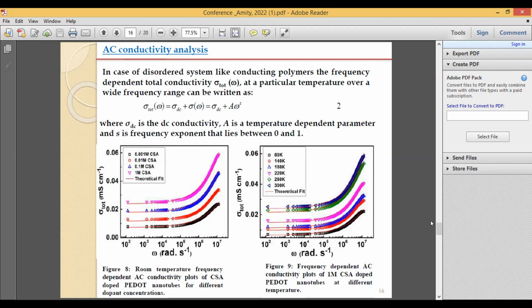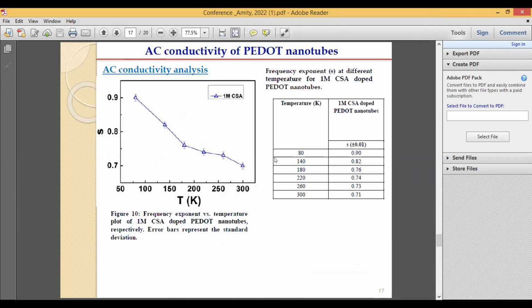doped sample at different temperatures with this equation number 2. From there we have found the value of S, and it is seen that the value of S is found to decrease with increasing temperature. We performed this from 80 Kelvin to 300 Kelvin. This suggests that the transport mechanism in our case is correlated barrier hopping, because if S decreases with an increase of temperature, then we can say that correlated barrier hopping is present in our system.